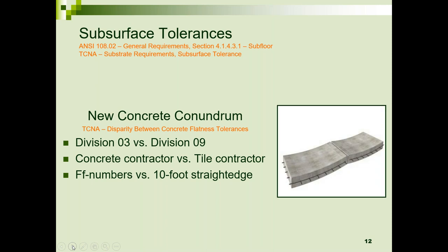And the reason for that is concrete as it dries will shrink and curl at the edges and the joints. So concrete that is flat 3 days after pour is not necessarily going to be flat weeks or months later when the tile contractor has to install tile. So even the flattest concrete 3 days after placement is not going to be flat enough for a tile installation at a later date.